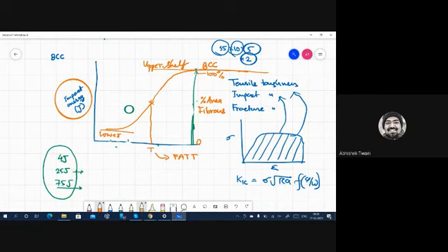So here you have touched the minima, and the energy cannot go below 4 joules. Because I think it will not be measurable by the impact testing machine if it goes below 4 joules. If it goes below 4 joules, that means you can break the steel sample with your hands, but you can't do it because the specimen is at -196 degrees Celsius. So you can use your hands with a glove, but not your bare hands.